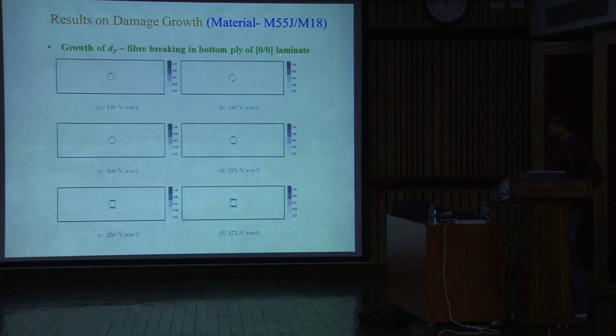This is a 0-0 laminate, a very simple laminate, and this is the growth of the fiber breakage. In this, we have considered a laminate with a hole, and the load is applied along this axial direction. So this is the evolution of the damage, the fiber failure.